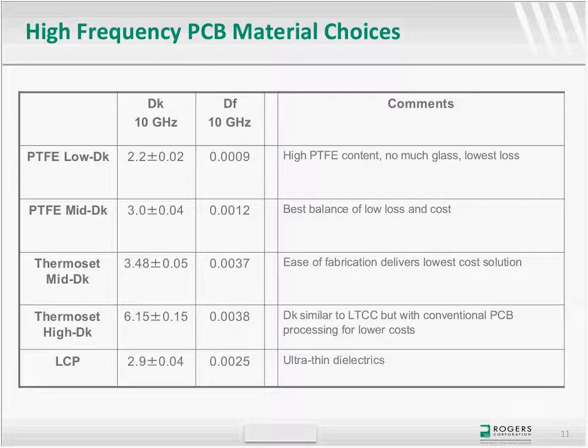in some multi-layers. It's a thermoplastic, so usually what's called sequential lamination, where you may have to have buried vias, and your process would not accommodate well here. But in a single-stage, multi-layer lamination process, this kind of resin system is good. 25, 50, 100 micron, 1 to 4 mils in thickness is common for these materials.